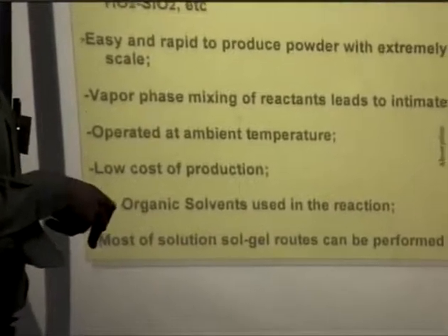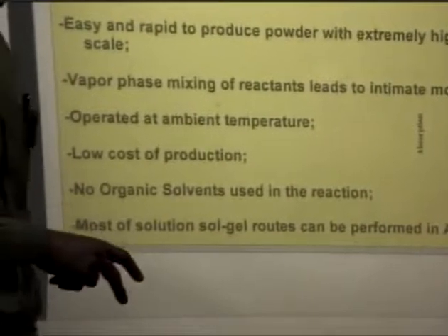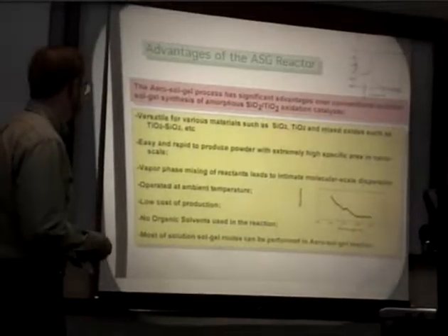Okay, if you put these in a beaker and react them, like just pure silica, it could take a day to make a gel that you would dry and make a powder from. In this case, it's happening in seconds. It's a continuous reaction, so we can just pump reactants in until we get sick of pumping reactants in and make as many as we want. It would seem that you could scale this up fairly easily.